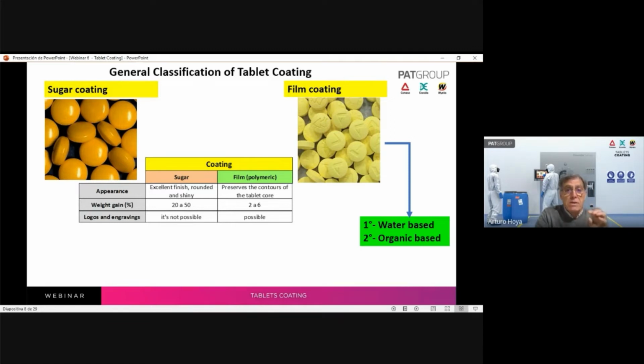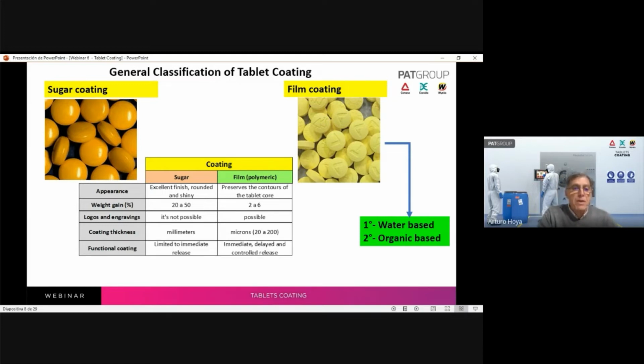Logos and engravings are not possible when you use sugar coating, but it's possible when you use the film. Look at the picture, the photograph. The coating thickness, the thickness of the film or the sugar. In the case of sugar, you have millimeters of thickness, and with film only microns, 20 to 200 at the maximum.